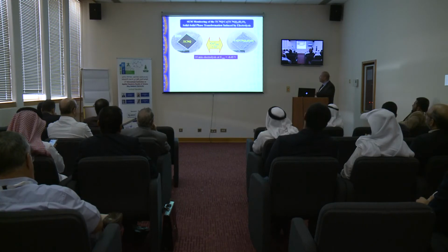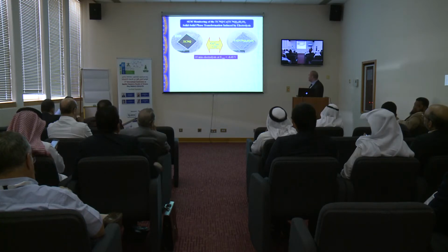We did also an interesting experiment. This is a drop-casted TCNQ. We dip it into a solution of cobalt. We reduce this by 1 electron for this applied potential for 10 minutes. We can see now that the whole crystal is still intact. However, it is fully covered with the features of cobalt TCNQ.